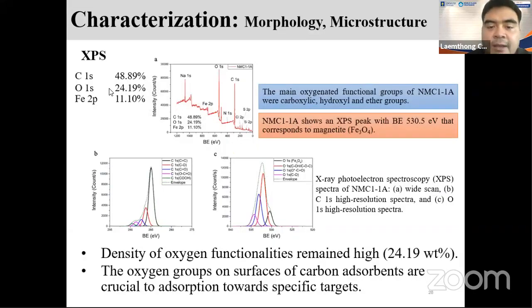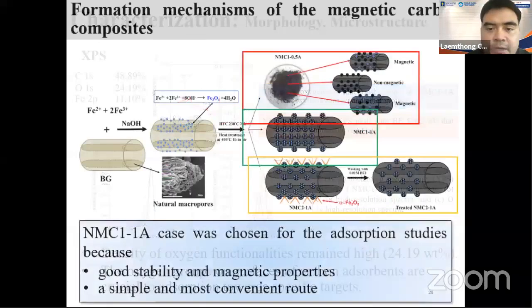As I said at the beginning, a carbon material as an adsorbent needs functionality. Because if we have suitable functionality, we can have interaction with our required contaminant, right? So in this case, I confirm that we still have a lot of oxygen functionality abundant in our system, which is suitable for adsorption because we can have hydrogen bonding with the stuff that we try to remove.